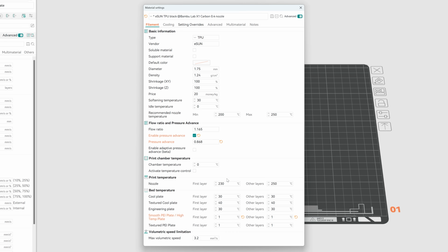Temperature tower. We settled on 230 degrees Celsius for the first layer and 250 degrees Celsius for the rest. Flow ratio calibration. Increased flow ratio from 1 to 1.165. And pressure advance calibration. We created a custom filament profile with a K factor of 0.868. So whenever we print something in Orca Slicer, we just select our new custom filament. And if we're using Bambu Studio, make sure the filament is also activated in the spool settings and that the correct pressure advance profile is selected.